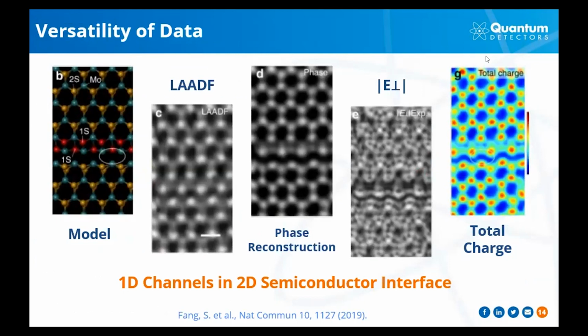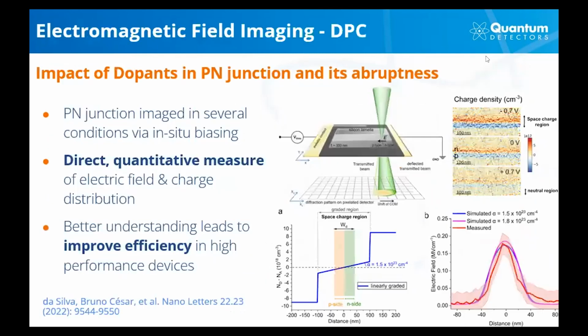So in this slide, I selected an example of how versatile a single data set from 4D STEM can be. On the left, we have these 4 images generated from MerlinEM data from a single acquisition: large angle annular dark field, phase reconstruction with a ptychography algorithm, in-plane electric field, and total charge together. And this information was applied to map the energetic landscape of this 2D semiconductor interface sample at atomic resolution. One of the first applications of 4D STEM was imaging of electromagnetic fields on the nanometer scale. In this example, by Bruno Cesar da Silva from Institut Néel in Grenoble, DPC imaging was used to image a pn junction, which was biased by a holder.